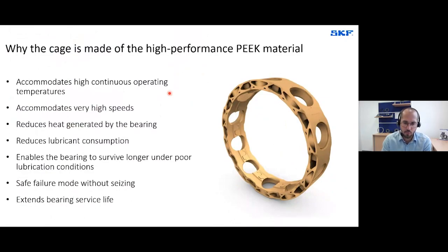I already showed before that we choose PEEK material for those cages, and it is very logical. PEEK is a polymer material, so it is light. It can accommodate high continuous temperatures, which is very often present at high speed applications. It generally reduces also the heat generation and lubricant consumption inside the bearing. And in general, as a consequence, it enables a reliable solution and increases service life at high-speed applications without any risk of sudden failure.